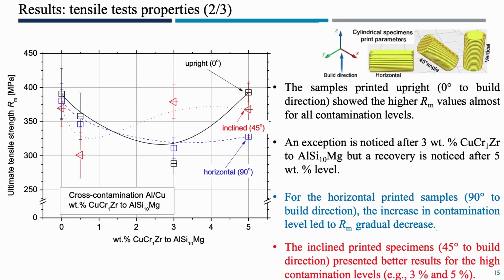Regarding ultimate tensile strength, here you can see that in general, for the low contaminations you have a decrease in ultimate tensile strength, but with the higher contamination, of course, the ultimate tensile strength reaches the nominal values without any type of contamination. Of course, this is due to the intermetallics and the copper addition.